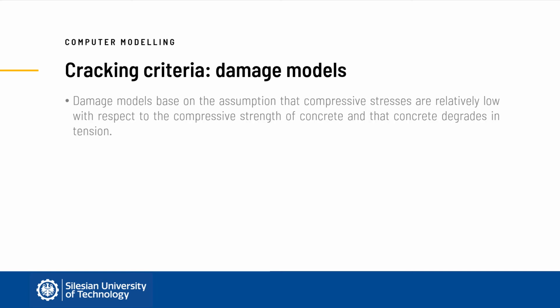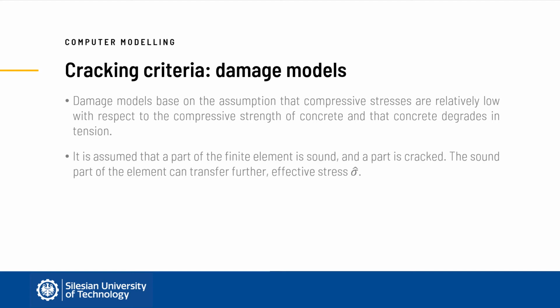Once the cracking is initiated, the behavior of the cracked material must be defined to follow the progress of cracking. This behavior is described by damage models. Damage models base on the assumption that compressive stresses are relatively low with respect to the compressive strength of concrete and that concrete degrades in tension. It is assumed that a part of the finite element is sound and a part is cracked. The sound part of the element can transfer further stresses.